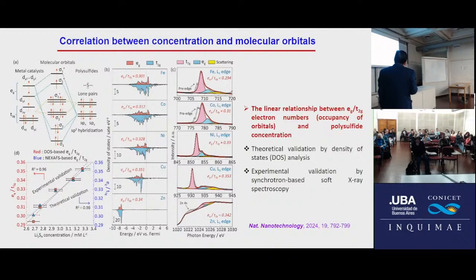How can we get this number? First, we can use the DOS. This is a simulation calculation. You give the material, we can get this number. For iron, copper, the different catalysts, this number we can calculate. This number can also be obtained from experiment. This is a synchrotron result. From the synchrotron, we can measure this number for different catalysts. Take a look, this is very close to each other, right?